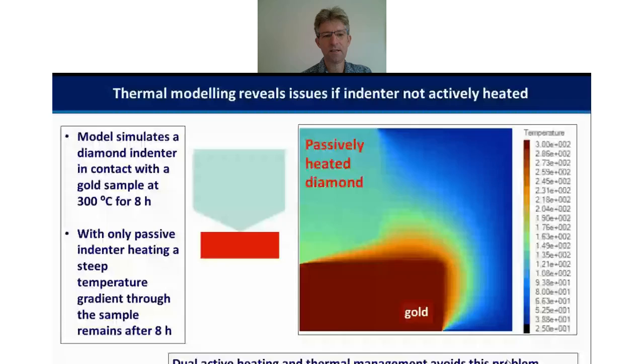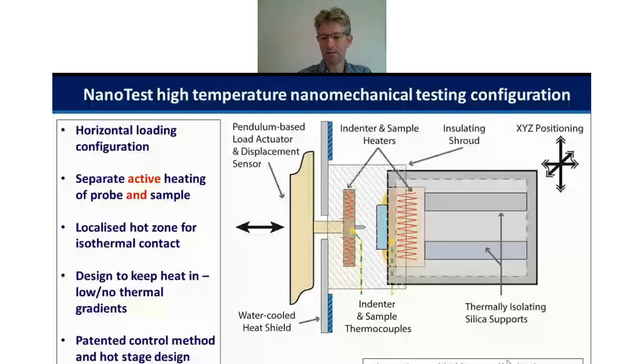You have this very steep temperature gradient, which can exist, particularly at higher temperatures. And this is an example here. The way to avoid it is to actively heat both the tip and the sample, and to precisely make sure those two things are at exactly the same temperature. So in the Micromaterials NanoTest system, we achieve that by a combination of things. We have a horizontal loading configuration, which is particularly useful because it allows any heat rising upwards from convection not to reach the displacement measurement electronics.